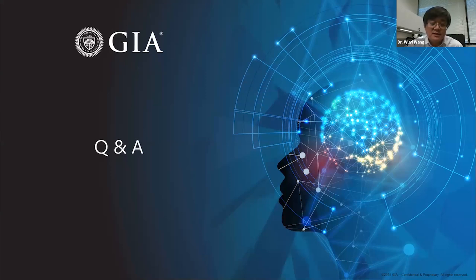The fifth reason for green, I showed you a couple of pictures of a chameleon diamond that show a pretty clear green body color. What is responsible for that green, we don't know. Exactly the physical model, we don't know. But that could be another reason for a green color. The sixth one could be nickel. Nickel is a very common defect in natural diamond and in HPHT synthetic diamond. Some natural green diamond is attributed to the nickel defect. So I talked about six, and there could be a couple more very minor, not major, defects that could also create some green colors.